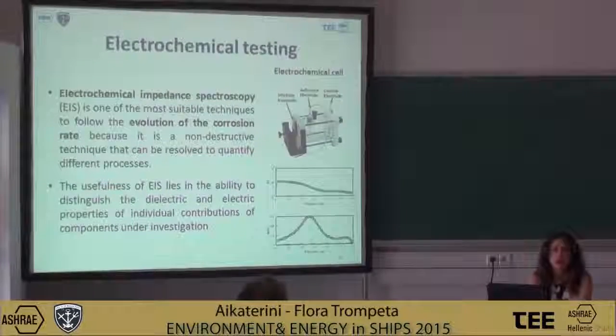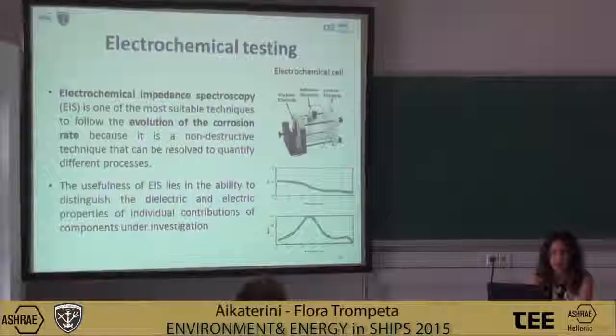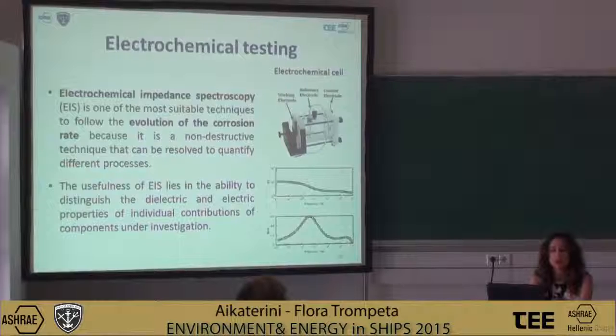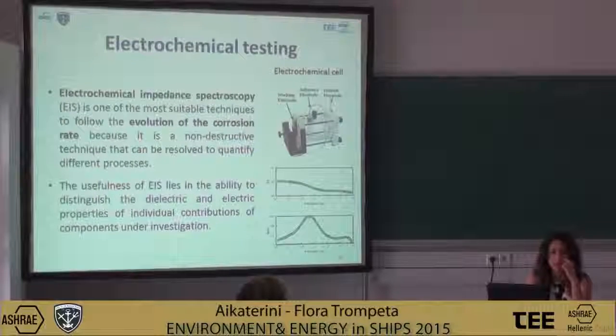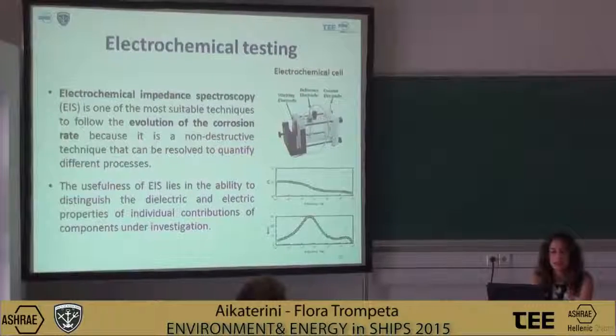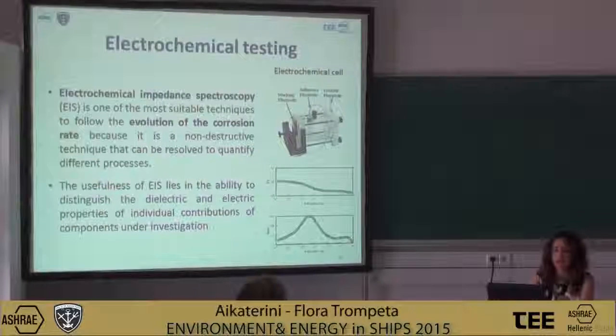Also, we performed the electrochemical testing using electrochemical impedance spectroscopy, which is one of the most suitable techniques to follow the evolution of the corrosion rate because it's not a destructive technique. The usefulness of the impedance spectroscopy lies in the ability to distinguish the dielectric and electric properties of individual contributions of components under investigation.